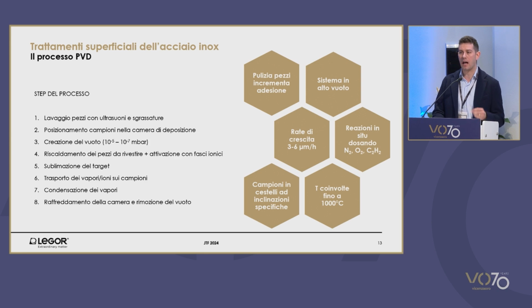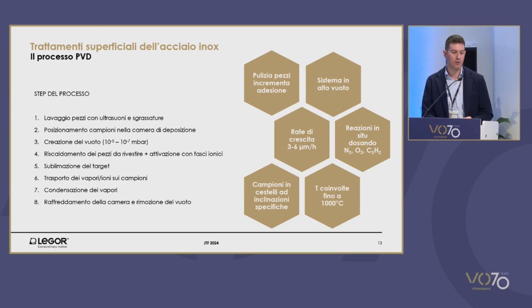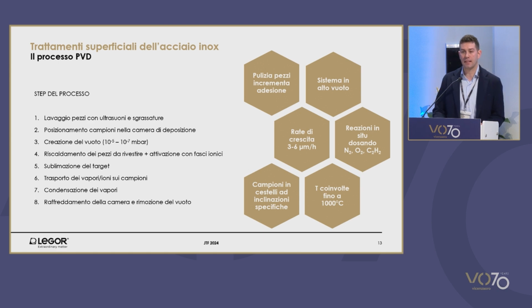As is the case of any electroplating, you have to do away with impurities so as to improve the adhesion of the vaporized materials on the substrate. So the sample is then placed on baskets in the deposition chambers. The baskets are oriented so as to promote the adhesion of the coating.